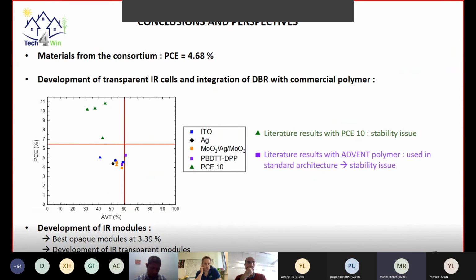So to conclude, with the materials from the consortium, we achieved only an efficiency of 4.7%. So we decided to develop transparent infrared solar cells with a commercial polymer. And if we compare our results with the literature, we can see here in green the literature results with the PCE10 or the PTB7-Th polymer. The efficiency is very high, and the transparency is about 40%.